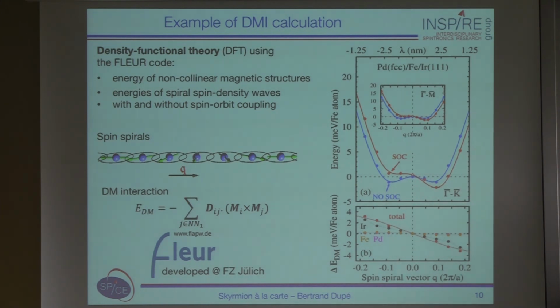So now if you turn on spin-orbit coupling, the situation is different. You see that this left-rotating spin spiral minimum is destabilized. This point here goes up, and now you stabilize a right-rotating spin spiral. So it's really spin-orbit coupling which stabilizes a right-rotating spin spiral in palladium, iron, iridium.